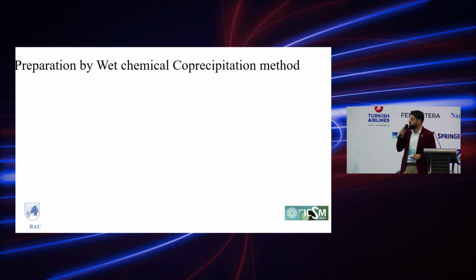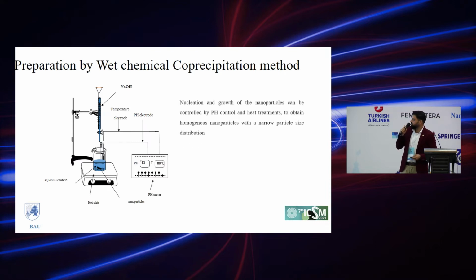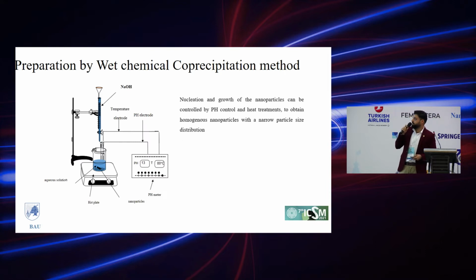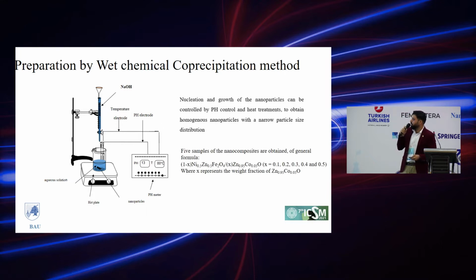Concerning the preparation method, we followed the wet chemical co-precipitation method, which is a chemical technique based on nucleation and growth, by controlling the pH and performing heat treatments to obtain homogeneous nanoparticles with a narrow particle size distribution. We obtained 5 samples of the nanocomposites of general formula (1-x) nickel-zinc ferrite with x zinc cobalt oxide, where x varies from 0.1 to 0.5 and represents the weight fraction of the zinc cobalt oxide.